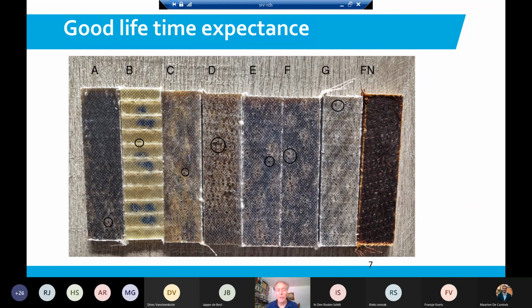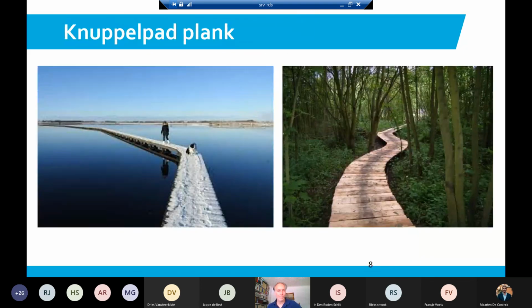So this is a very important measure if you want to use these products outside in the weather. And the good thing of these samples was that the lifetime expectancy of the grass fiber together with this furan-based resin is very good. It was much better than the other resins we tried to use. So that's a good step.